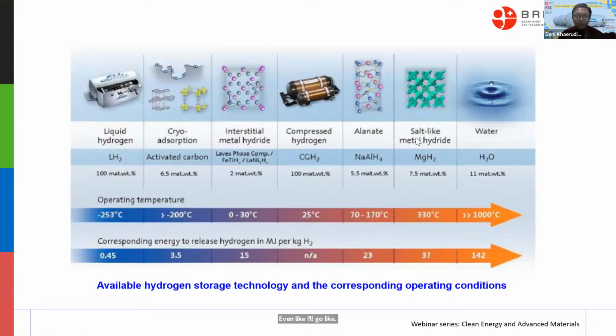Okay. This is the condition of each storage technology, like in the liquid. So the operating temperature is minus 253 again, and this is the corresponding energy to release hydrogen in megajoule per kilogram hydrogen. You can see here the compressed one, and also the alanate and metal hydride. And then the water itself, of course, just for comparison. If you want hydrogen directly from the water, you need more than 1000 degrees C. So for sure this is not feasible for industry.